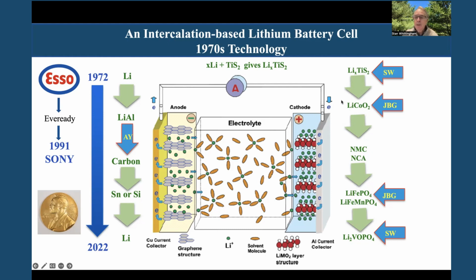John Goodenough, who was working on the magnetic behavior of lithium cobalt oxide at that time, recognized the similarity of the structures and tested this in an electrochemical cell and showed that lithium cobalt oxide worked. And this is now what's in most of your small devices. But cobalt is expensive. It comes from the Congo, and a lot of child labor is involved. So there's a big push to remove the cobalt out. So most of these layered oxides now contain nickel, manganese, as well as cobalt, or in the case of Tesla, contain nickel and aluminum with the cobalt. But our goal is eventually to get all the cobalt out.